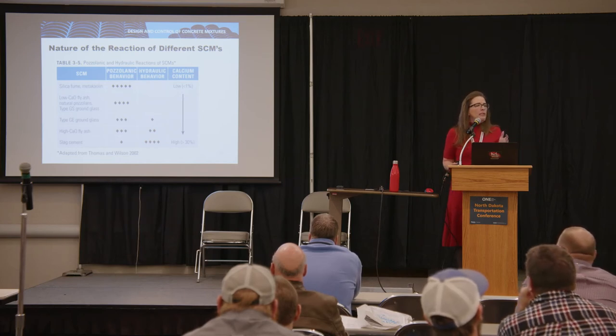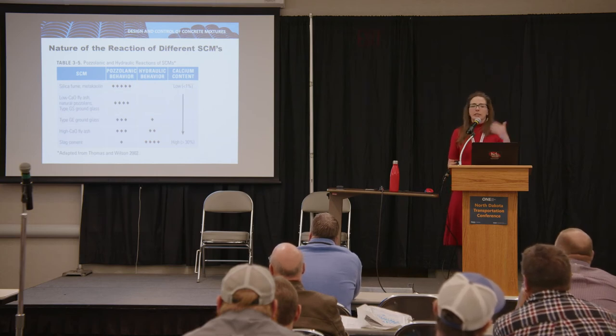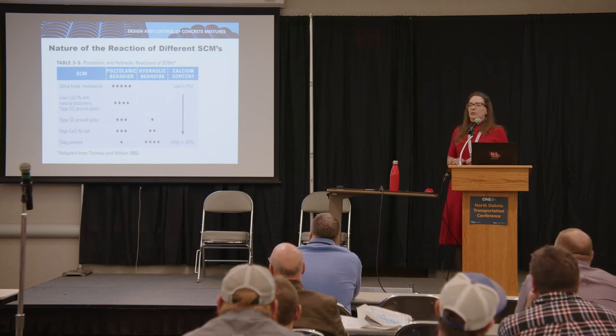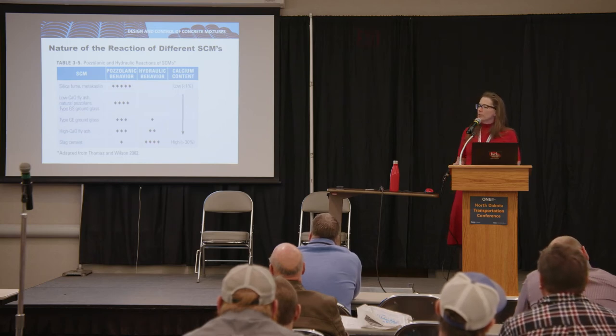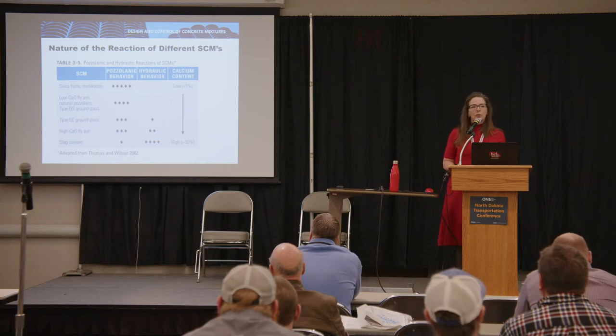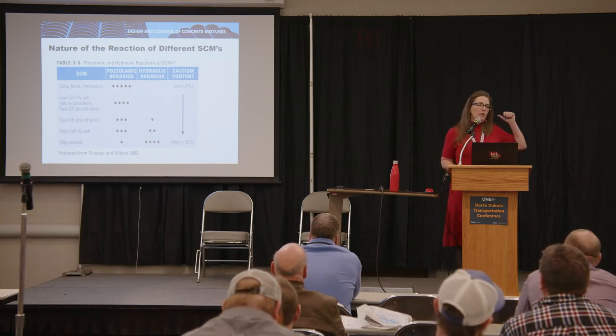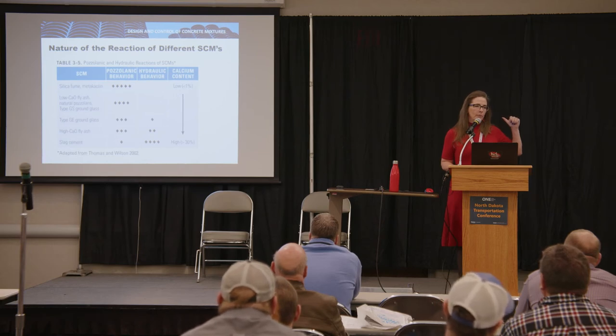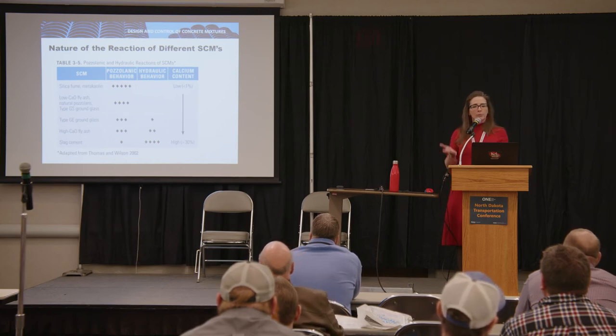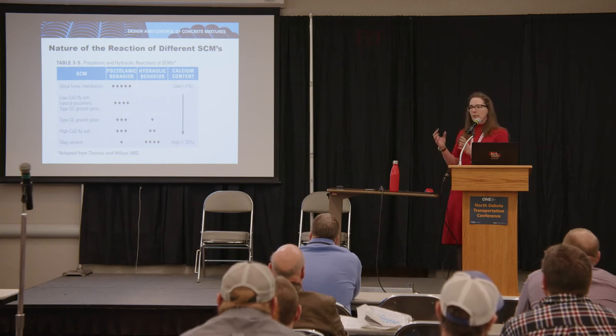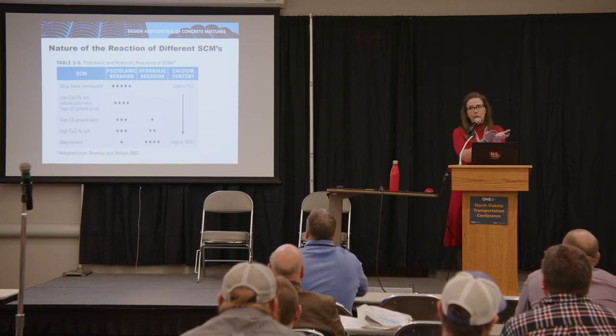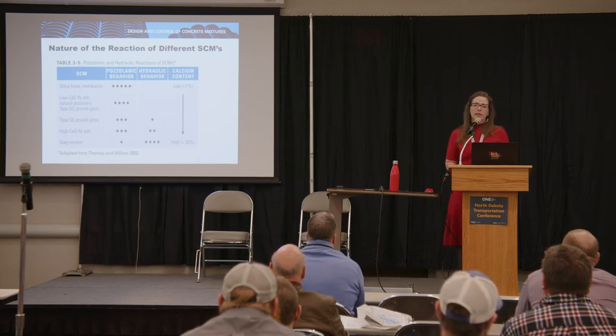If you're above 18%, up to 30, that is a C ash, and less than 18 is a class F. But now it's getting even more confusing because depending on your coal sources, you're probably blending coals and you probably have a combination. It's not about if it's bituminous or subbituminous, and you really just need to get over it. What you want to know is how much calcium is in this SCM and how that impacts its pozzolanicity. So is it a hydraulic material or is it pozzolanic? Why do you care? Because when you woke up this morning, you were thinking about calcium hydroxide and how much silica was available to bond to it to make calcium silicate hydrate, the beautiful gel that some people call mud, that gives us our strength and durability. That's how we get durable concrete. So this kind of stuff is important to us.